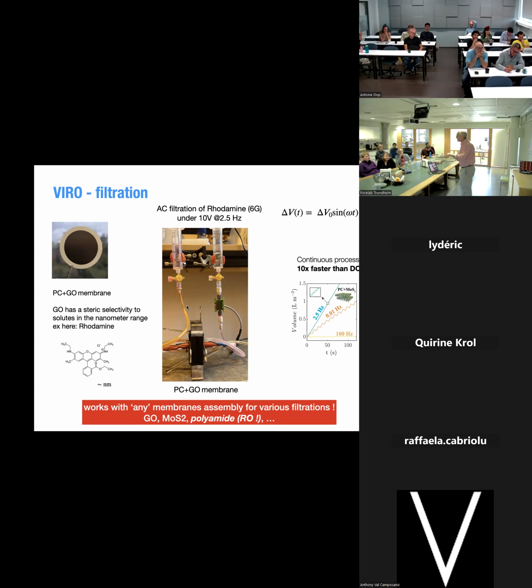Okay, I will skip all the discussion about the optimal frequency, because there is an optimal frequency there, resonant-like, but whatever. What is nice is that you do this filtration here for rhodamine, but you can choose the selective parts. We played a lot with graphene oxide and MoS2 because they are easy to fabricate in the lab. But you can also use polymer membranes which you glue to the polycarbonate membranes. These polymer membranes are desalination membranes, meaning you can really desalinate.